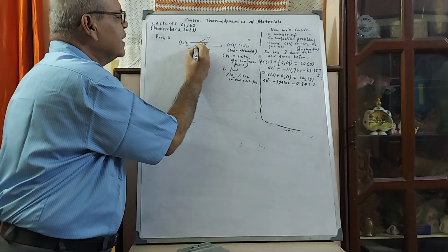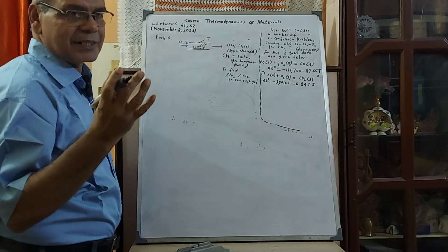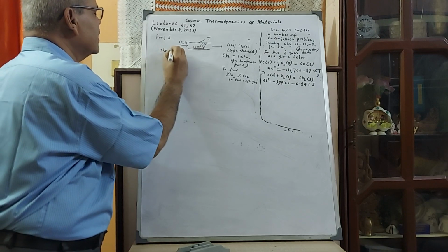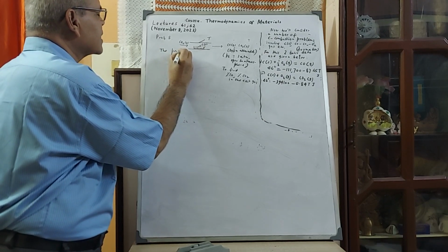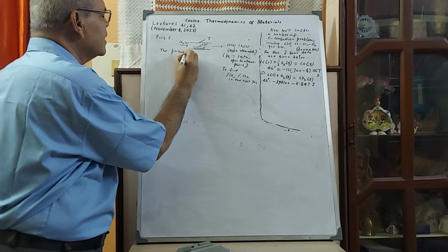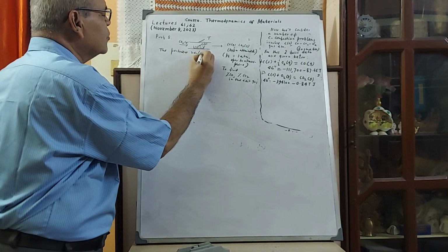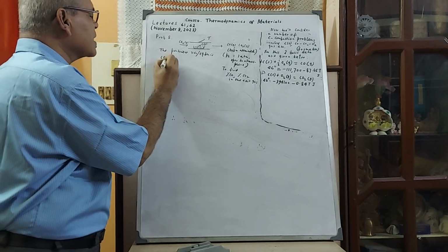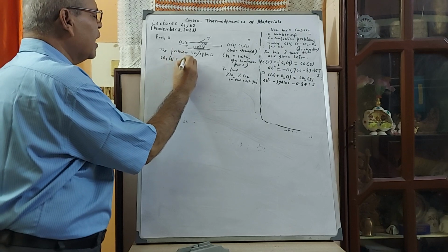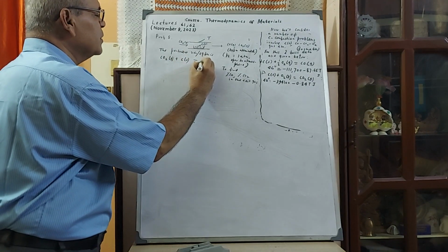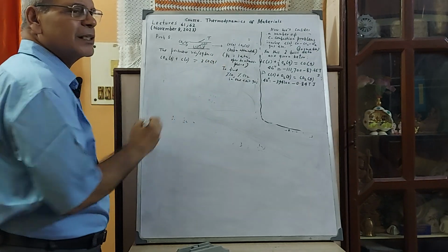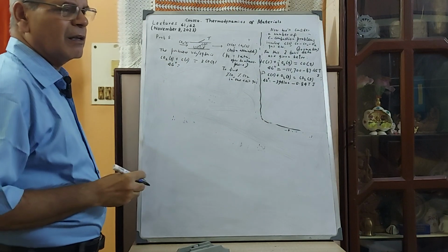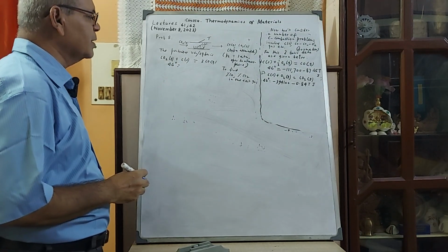So follow, gas with carbon reacting. So what is your reaction? So the pertinent reaction, or equilibrium as you call it, let me write nicely: CO2 gas plus C gives 2 CO gas. You follow, since you are actual beginners. Soon you will be very expert. This is the delta G0 for CO2 plus C giving 2 CO gas.